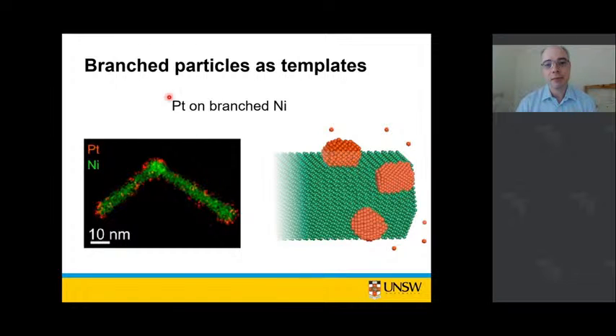So this is looking at platinum nanoclusters, platinum islands on branched nickel particles. So this is now using our branched nickel particles as the seed. And this is some of the particles that we made. So you can see your branched nickel structure, and all of these red dots are basically the platinum islands decorating the surface of the branched nickel.